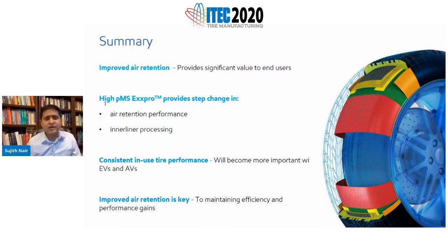So just to summarize, we believe that air retention will play a much more critical role in the future, especially with the advent of EVs. So we believe that improved air retention will provide a significant value to our end users. High pMS Exxpro, so Exxpro 3563 in particular, provides a step change in air retention, and it also provides several other advantages as far as processing is concerned. We believe that consistent in-use performance is going to be more and more important with electric vehicles, with vehicles going towards full fleets with autonomous driving, because again, it's a safety factor. The more you lose air in your tire, the more susceptible it is to catastrophic events.